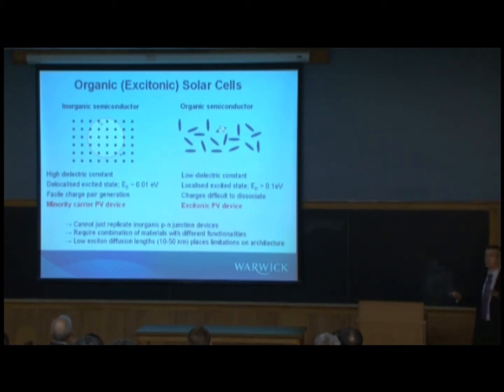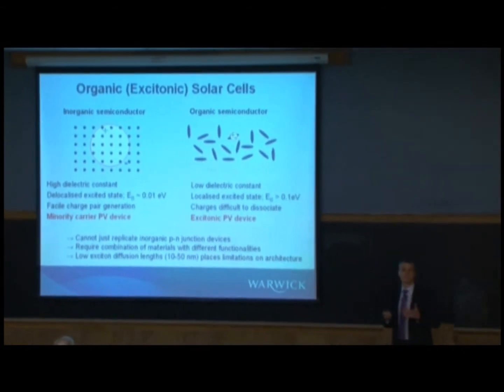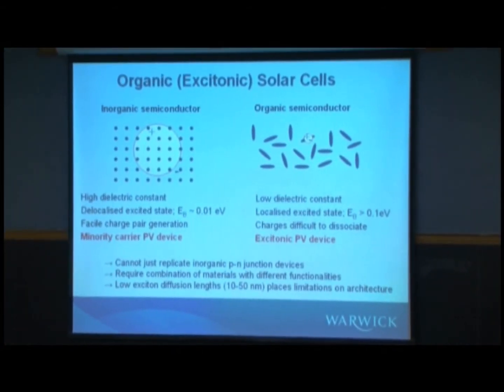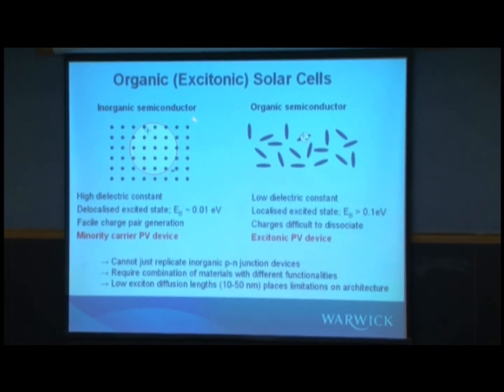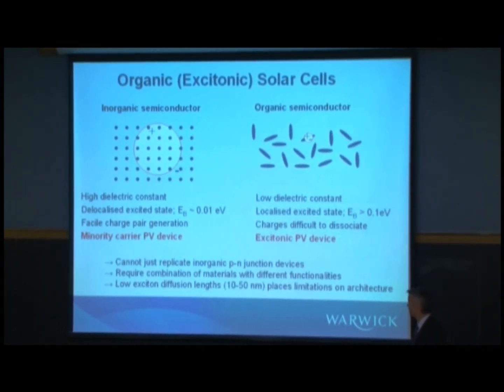So the first and second generation cells, silicon, cadmium telluride, copper indium gallium diselenide, and so forth, those are inorganic semiconductors. And in an inorganic semiconductor, you have a high dielectric constant, a delocalized excited state with a very low binding energy, 0.01 eV, something of that order. And so separation into free charges, into electrons and holes, so you can generate a current, is a very easy process. It's a facile process. And so the PN junction, which is used throughout the electronics industry for silicon and other semiconductors, is the bedrock of the inorganic solar cell.